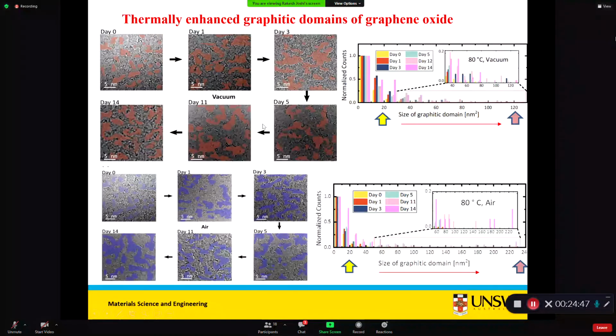We see that in both cases the graphitic domain size, this is the image software, we did a lot of extensive TEM study to see the graphitic domains. We can change the size of the graphitic domains from nearly 20 nanometer square, the day 0 is the yellow one, to more than 200 nanometer square. And both of these techniques keep the functional groups intact. The concentration of functional groups doesn't change much. We did NMR study for that, and then more TEM studies to see the graphitic domains.